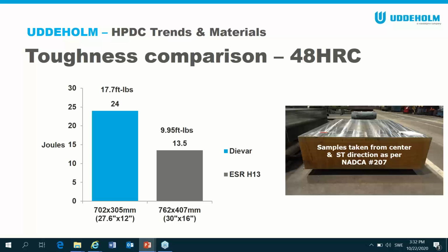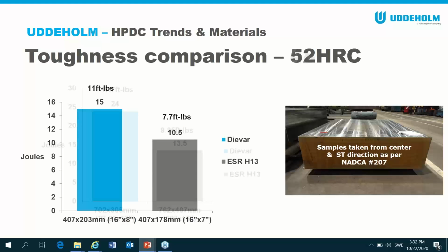So you see here we took stock cross sections, so bigger cross sections at the mill. We heat treated them just to see what we would get. At 48 Rockwell in Dievar we've got 17.7 foot-pounds, and in our Supreme we've got 10 foot-pounds. A big difference between the two materials, and this just carries on as you go up higher. Now remember, the minimum level he talked about was 8 foot-pounds. And at 52, we've reached the limit with our Supreme, with 7.7 foot-pounds. But in Dievar, you've got 11 or 12, compared to 10.5.